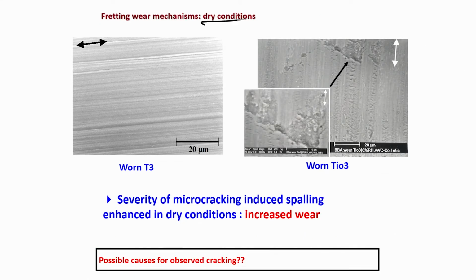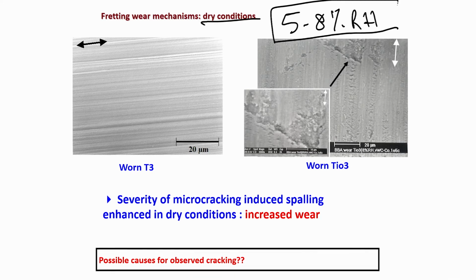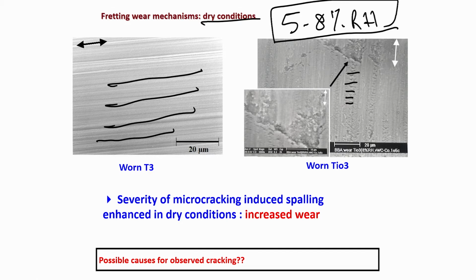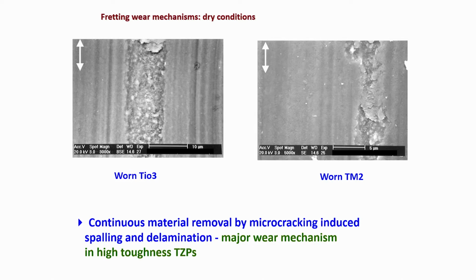Now, let us look at some other observations. What happens in the dry conditions? You remember that we have also done the test at 5 to 8% relative humidity conditions. Here the severity of the abrasive scratches increases, and that corroborates well with the wear volume of this material. But what is more interesting is that even the microcracking perpendicular to the fretting direction also increased in severity. In some of the cases we have found a very clear signature of spalling. So, this spalling is increased at very dry conditions, and that leads to increased wear of these materials.